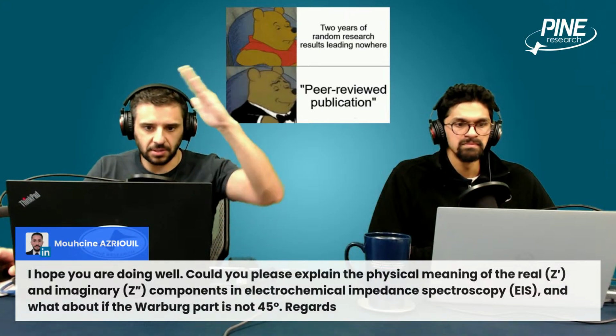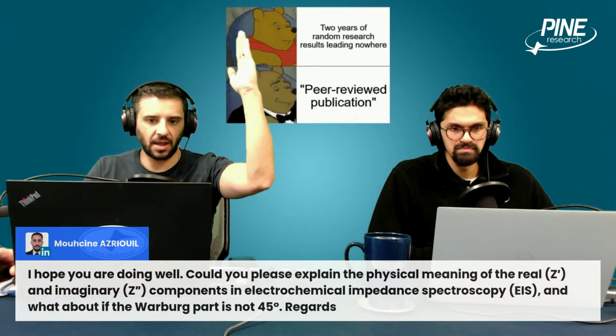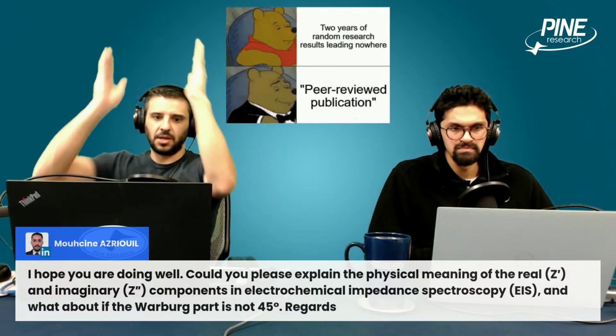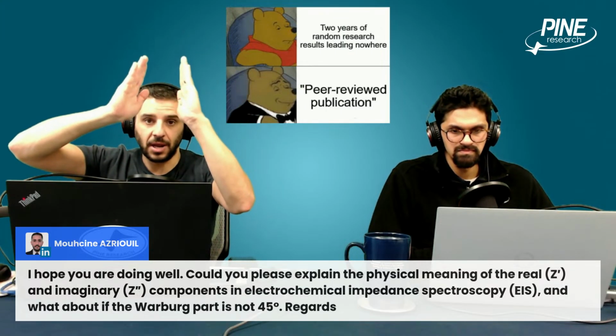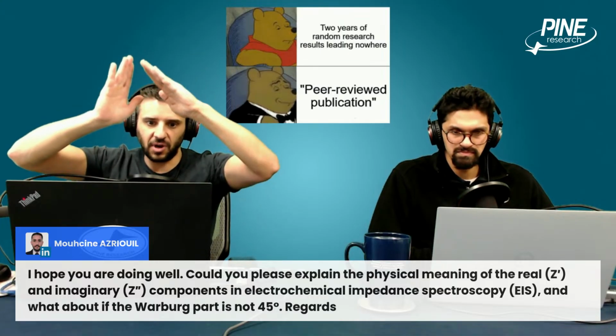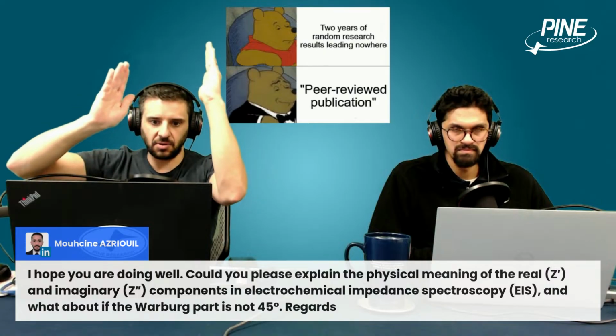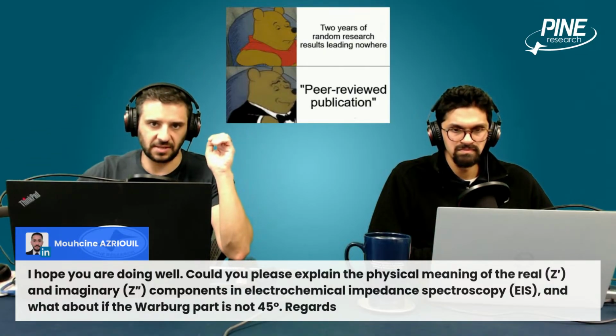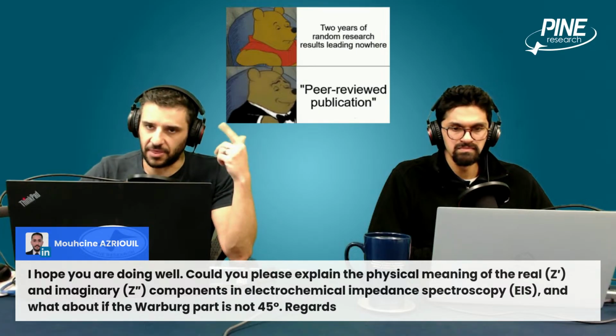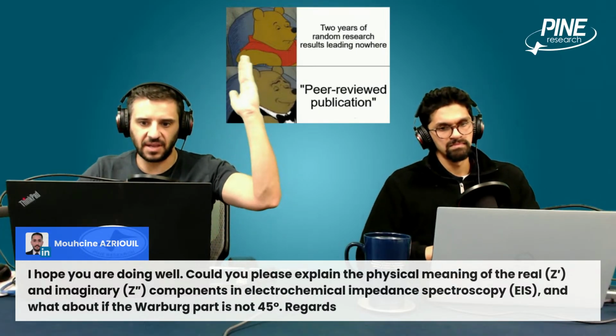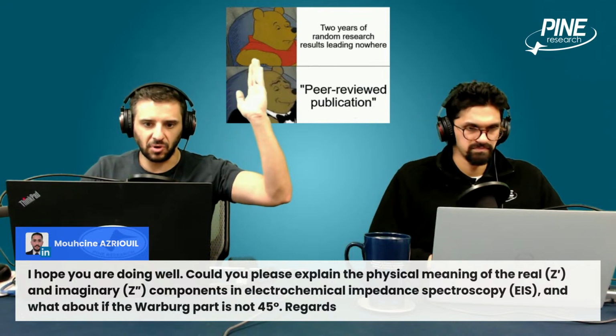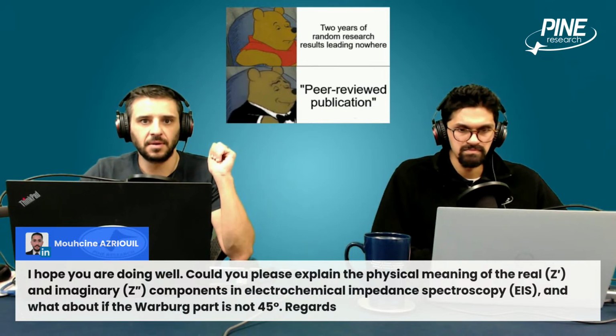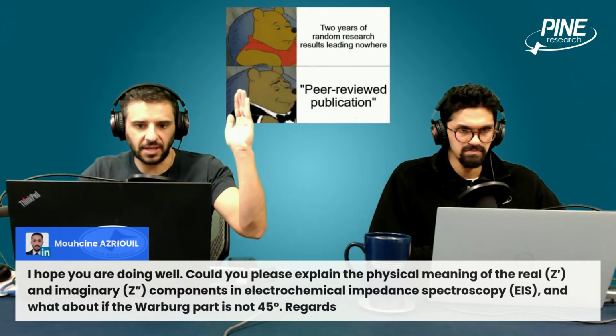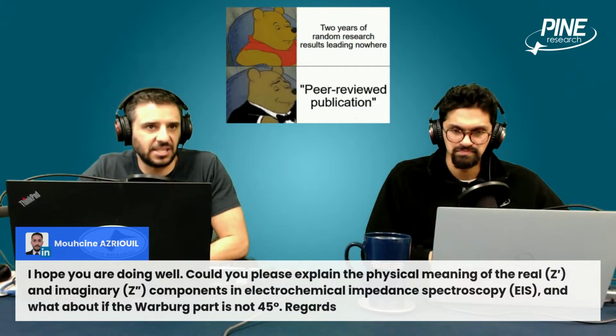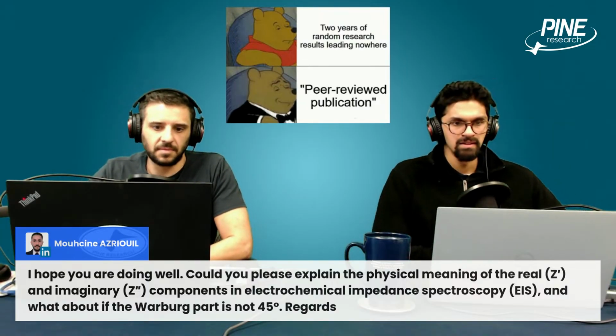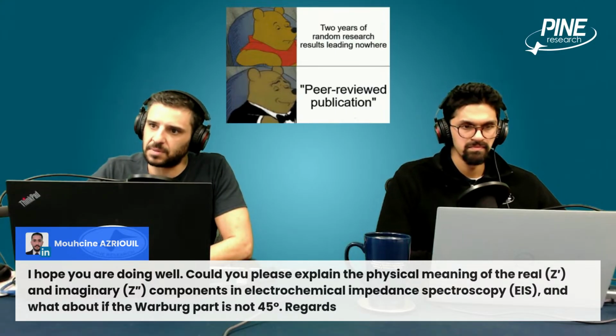A 90-degree angle on the Nyquist plot is a perfect capacitor, which is like two planes at some distance from each other, not moving at all, zero movement. So at 45 degrees, it's moving. At 90 degrees, it's not moving at all. As a very simple thought concept, any angle between 45 and 90 degrees is something between moving at a normal diffusion speed and not moving. It's like moving but more slowly. So something like non-ideal diffusion or slower diffusion, mostly capacitive, but the ions are moving.